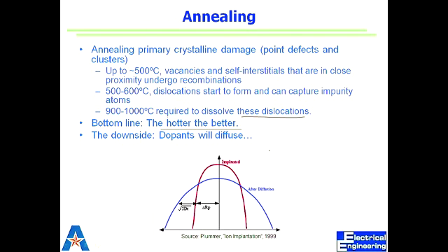The whole wafer goes in for oxidation, so I have to know that high temperature will cause that implantation to diffuse as well. This is then accounted for in the whole process. So instead of doing that drive-in or annealing for a longer period, we leave it to happen during, for example, the oxidation process that's going to come afterwards.